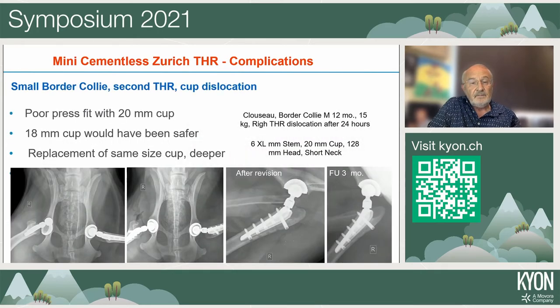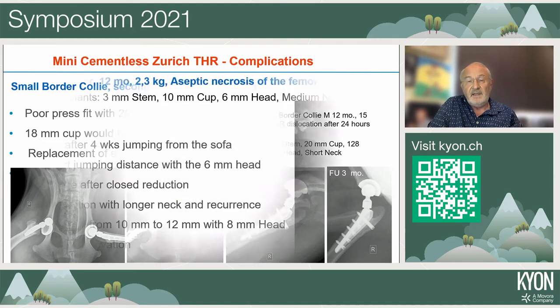The second complication was a cup dislodgement, and that was most probably because a 20 millimeter cup was too big for this very small border collie, 15 kilogram. That led us to understand that it's better to stay with a smaller cup, but to have good bone stock cranially and caudally to provide a good press fit. Anyway, we went back and replaced the same size cup, but going deeper in such a way to have more bone contact and more press fit. And the follow-up at 3 months is okay.